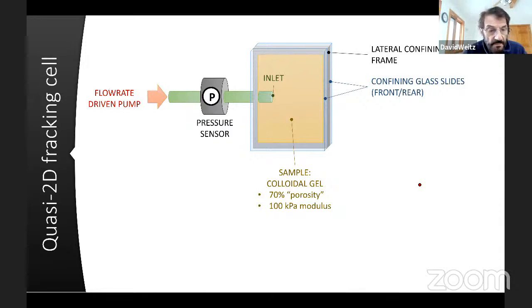So let me go back to the experiments that I was telling you about with these colloidal gels. The sample is Ludox, that's colloidal silica. The size of the particles is a few nanometers in diameter. And with a variety of methods that are actually very well known from 30 or 40 years ago, we know how to induce a reaction that causes the otherwise stable particles that are moving around freely in the fluid to join together and form a gel. It's a colloidal gel. Its volume fraction can be between a few percent and 20%, 30% is very high. And it's relatively clear, so you can see through it, so we can do scattering experiments.